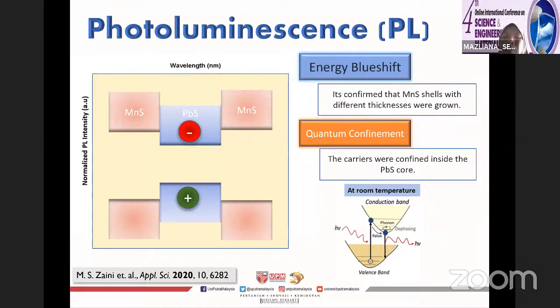So when we sandwich the PbS core, creating the exciton needs higher energy. We also did the calculation. My colleague calculated the confinement of charge carriers in lead sulfide, manganese sulfide type 1 quantum dots using the effective mass approximation. She also found that when we increase the thickness of the shell, the confinement energy also increases.